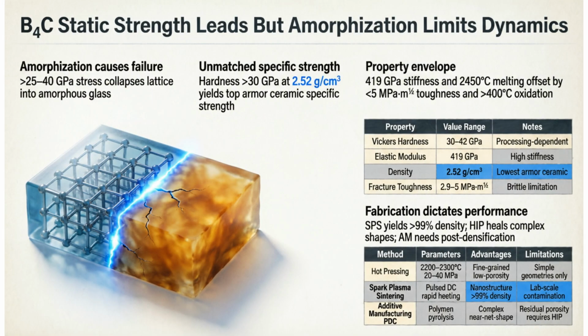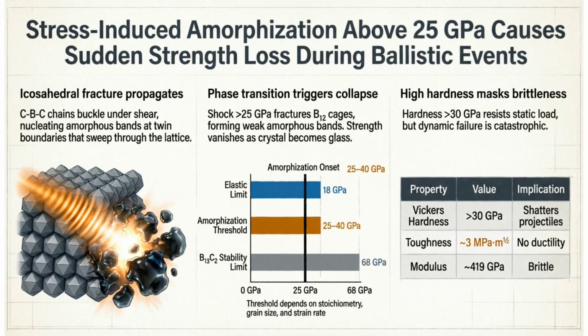Ultimately, boron carbide offers unmatched specific strength, yet its dynamic utility is capped by amorphization. Performance relies on selecting the right fabrication method for the application. During ballistic events, stresses above 25 gigapascals fracture the boron 12 cages. This leads to the formation of amorphous bands and a sudden, catastrophic loss of strength.